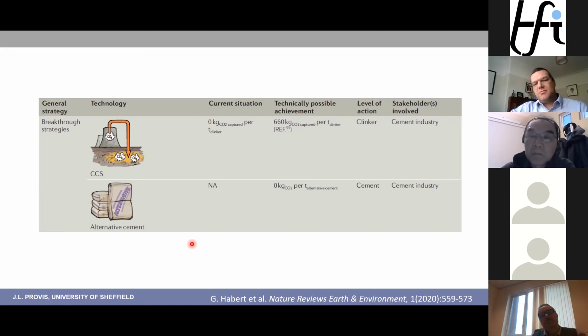We can look at alternative cements. And it is technically possible to produce cement at 0 CO2 attributed emissions. It's not easy. A lot of alternative cements are looking at savings between 20%, 40%, 60%, some up to 80% savings. Now, in most industry sectors, if you say, oh, I've got an option that will save 20% of CO2 emissions sector-wide, you'd be having people bashing your door down. In the cement sector, the tradition is someone launches a cement and says, this is zero carbon. And then it actually turns out it's not quite zero carbon. Oh, it's not zero carbon. You're only saving 60%. You're only saving 50% of the emissions.